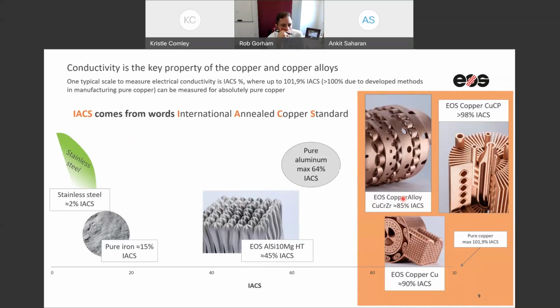And of course, copper alloys, which are again very popular with the rocket industry, where they're alloyed with hardening components like chromium and zirconium just to add strength. So they are not only able to conduct heat at a higher ratio, but they're also able to withstand pressures that are coming with such demanding applications.